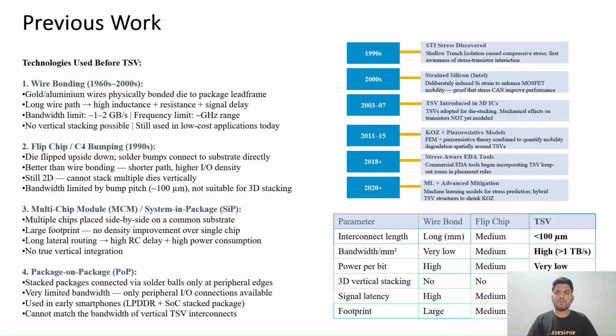Then came the flip chip or C4 bumping in the 1990s. In this method, the die was flipped and connected directly to the substrate using solder bumps. This reduced interconnect length and improved I/O density compared to wire bonding. However, it was still fundamentally a 2D integration method and limited by bump pitch, typically around 100 micrometers. Multi-chip modules and system-in-package placed multiple chips side by side on a common substrate. While this improved system integration, it increased the footprint and did not provide true vertical stacking.